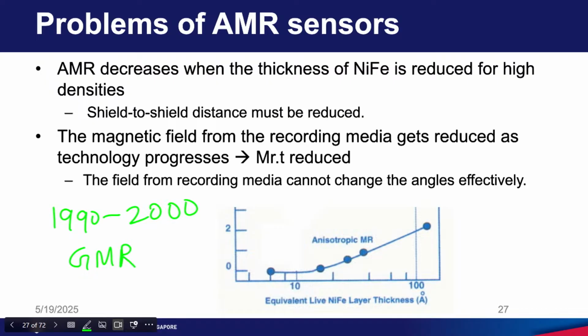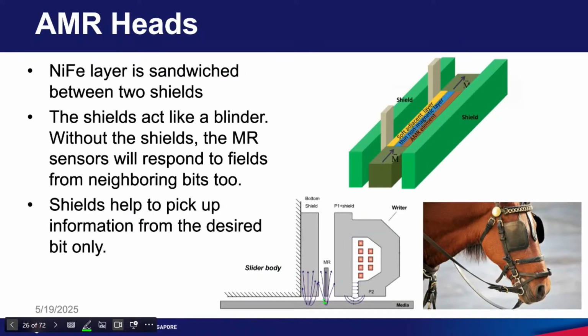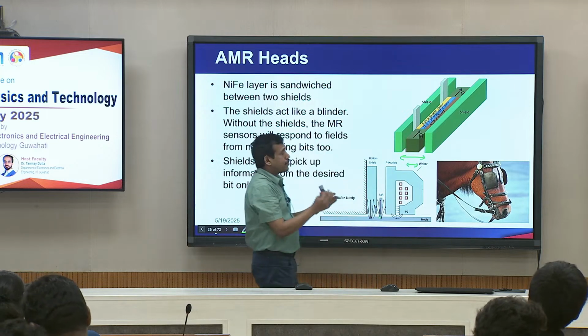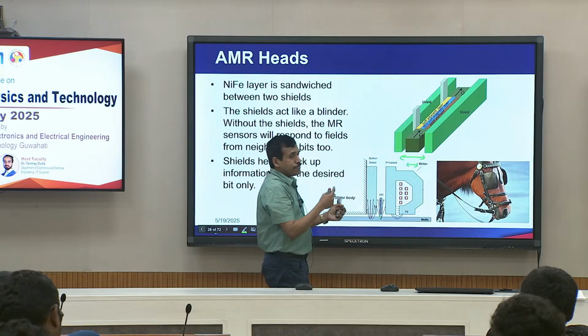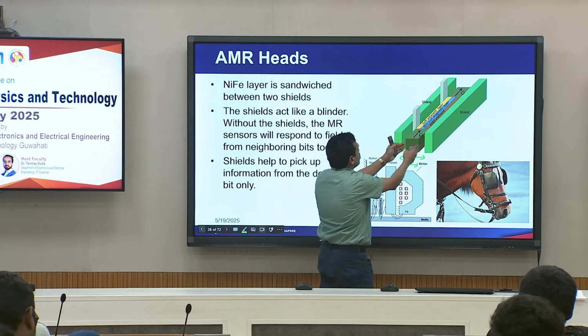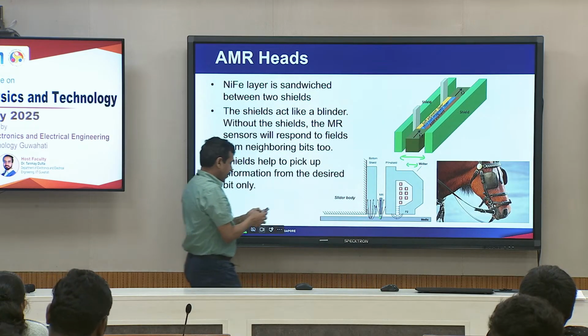Why this technology was used only for a very short time is because of the reasons I have shown here. For example, let us say you make an AMR sensor where the permalloy layer thickness is 10 nanometer. At 10 nanometer you have about 2% AMR. Now, I want to make the sensor smaller and smaller, as we discussed before, because we want the bits to be smaller. So, we want to go from this dimension to this dimension, and we need to make the AMR element thinner. We want to reduce the shield to shield spacing, because the bit length is going to be reduced. So, when you want to make this closer, the AMR element thickness has to be reduced.